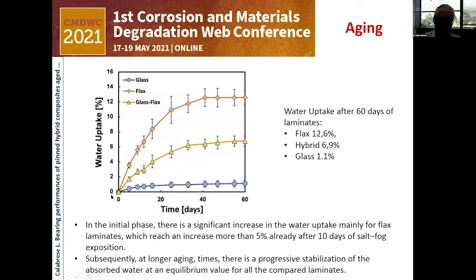But the important question is whether this information is influenced by aging, because we know that the natural fibers have a hydrophilic behavior, which favors the degradation mechanism of the composite material. Here I summarized the water uptake curves until 60 days for all laminates, with an evident low water uptake for glass, high for the flax one, which is the typical behavior of natural fibers, and the hybrid one that has roughly the half value for the two configurations.